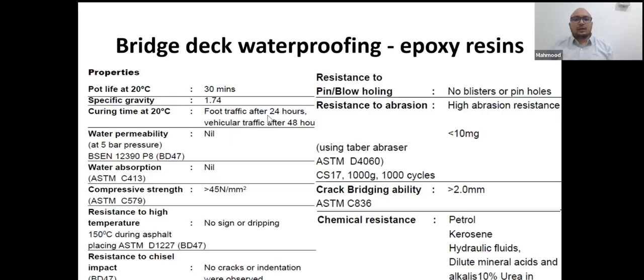Foot traffic can start after 24 hours, vehicle traffic after 48 hours. Water permeability is nil. Water absorption is nil. Compression strength is greater than 45 Newton per millimeter square. No cracking. Resistant to petrol, kerosene, and various chemicals.